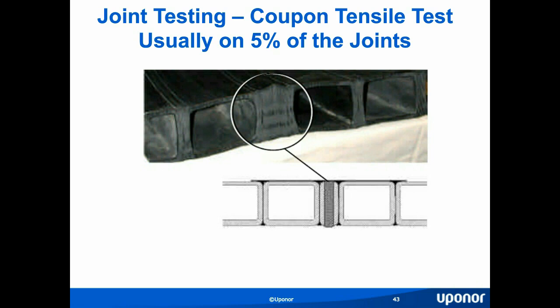So we generally test every 5% of the joints. There's this project that we just concluded a little while ago, and we were asked to take three coupons, one at the beginning of the project, one at the middle, and then one at the end. And they all passed with flying colors. And like I say, our minimum tensile pull on that would be 15 MPa. So we like to see it close to 20, 25 MPa.